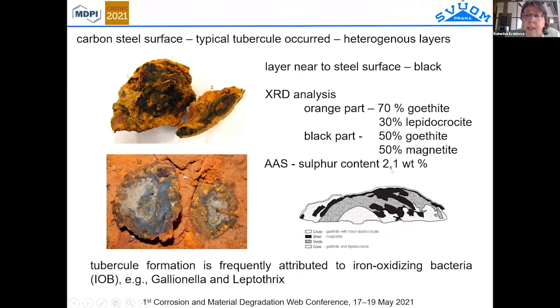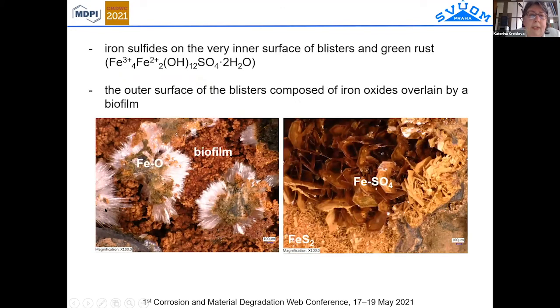The sulfur content in this layer, in this tubercule, was near 2%. The existence of such tubercules is usually connected with the existence of iron oxidation bacteria in the water system. And we look very deeply at the layer of corrosion products. We can identify the layer of biofilm, the layer of oxide, and also the layer of sulfides and the sulfates. So you can see how different the morphology of the surface is.